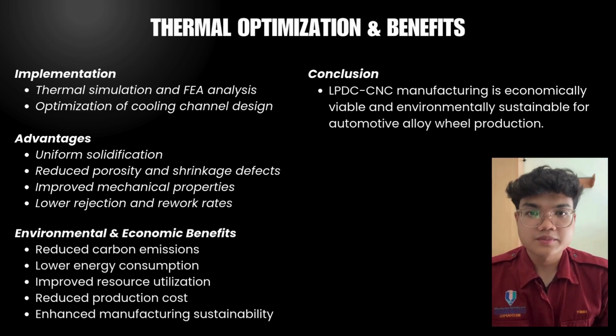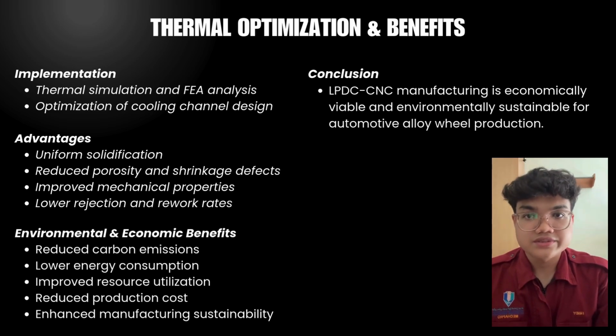Besides recycling, thermal modeling and process optimization can further improve manufacturing efficiency. By using thermal simulation and finite element analysis, engineers can optimize the cooling channels inside the LPDC die. This helps achieve more uniform solidification, reduces casting defects such as porosity and shrinkage, improves mechanical properties, and lowers rejection rates. As a result, less material and energy are wasted during production. Overall, the combination of aluminium recycling and thermal optimization provides several benefits, including reduced carbon emissions, lower energy consumption, improved resource utilization, reduced production costs, and enhanced sustainability.